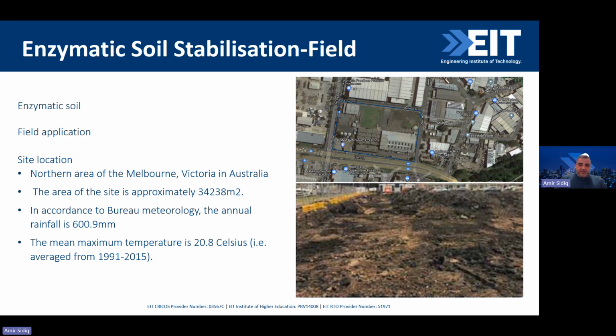Here, there was a work in the northern area of Melbourne, which consists of about 34,000 square meters. We have some statistical data: the annual rainfall in the area, based on the Bureau of Meteorology, is about 601 millimeters annually. The maximum temperature is about 20.8 Celsius as an average from 1991 to 2015. So we need to understand the background environmental information, such as the temperature and rain, because they all contribute to the shrinkage and swelling of this expansive clay material.